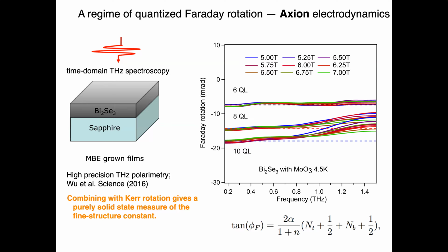And so we developed these ways of doing these high precision experiments, and we're able to measure the fine structure constant in a topological insulator to 5 decimal points. It's not as good, of course, as the atomic physicists do, but still not bad. Okay? And that's done in these particular experiments here, which let me not tell you about the details of.